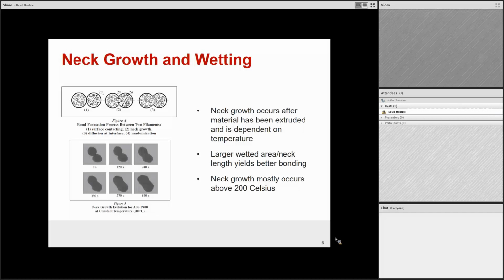And most, at least not that I'm aware of, they don't usually heat treat these parts once they're manufactured. It's like it pops off the printer and it's ready to go, right? Maybe there's someone who's heat treating them. Then you have to deal with slumping and all these other issues that could potentially happen. This is a long time to hold the part at pretty elevated temperatures, especially for polymers. I imagine that locally, a lot of this forms very quickly because it's coming in at a fairly elevated temperature, but it's not there for very long.